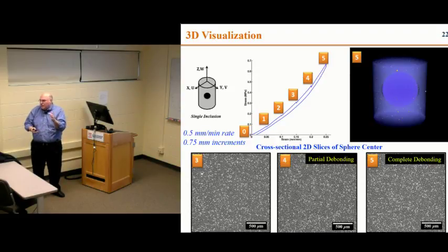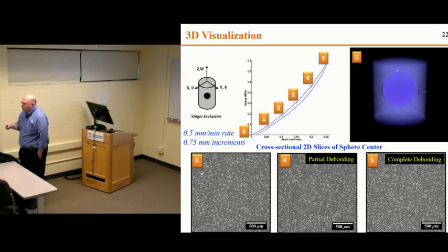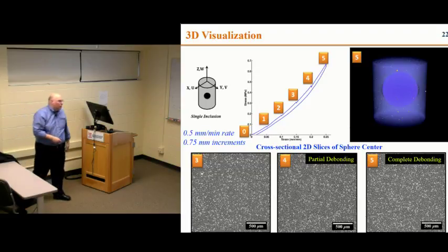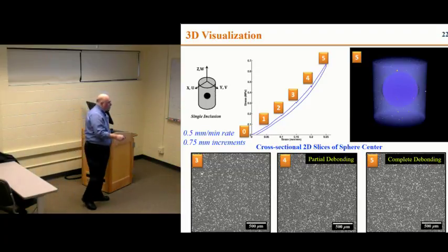The relaxation has always been a concern. There's not much actually, so we were pretty happy to see that this combination doesn't relax too much, right? So you can see a small load drop each time, and this is the relaxation while a scan is being taken, and everything is done in situ. And once the scan is completed, then you keep on loading.